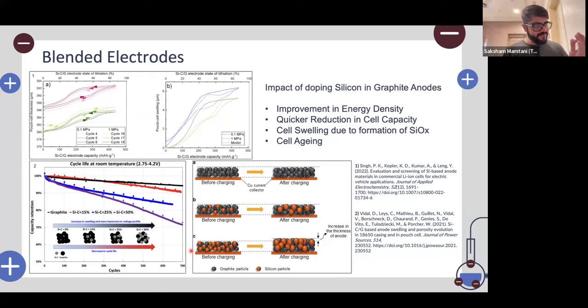In the past 12 years, we have seen researchers working on doping silicon oxide in the graphite anodes. And this has its pros. Definitely, it has its pros. However, it also has disadvantages, which the current R&D is trying to tackle. While doping silicon in graphite, it has been observed that it increases the energy density of the battery by quite a bit. The drawback is that it swells the battery quicker, so the retention of capacity fades very quickly.